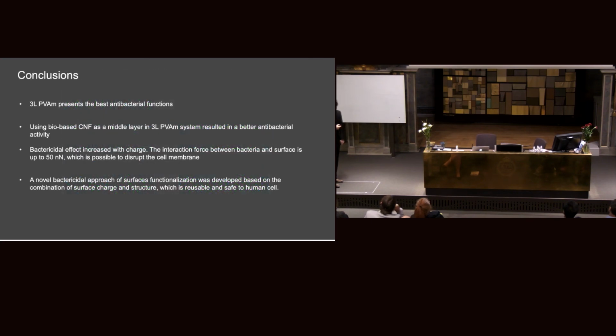So to wrap up this work: first, we found the 3-layer PVAm is outstanding and shows the best antibacterial functions among other cationic polyelectrolytes. And by using the bio-based CNF at the middle layer instead of PAA, it actually results in better antibacterial activity, which could be due to increased surface area and roughness.